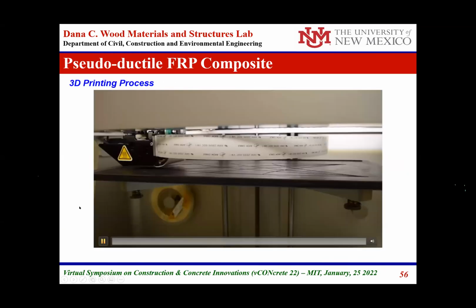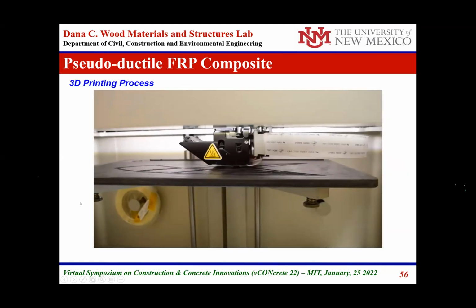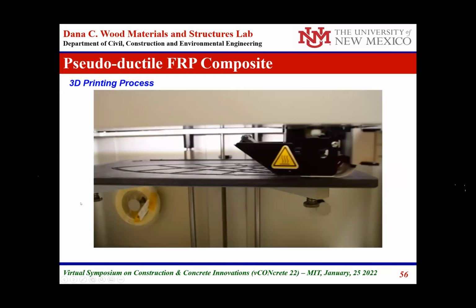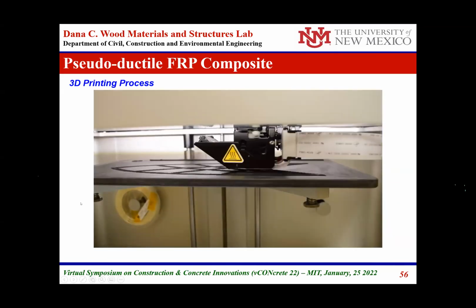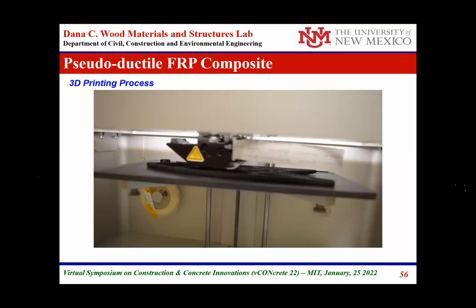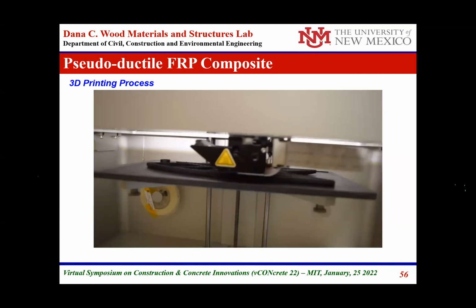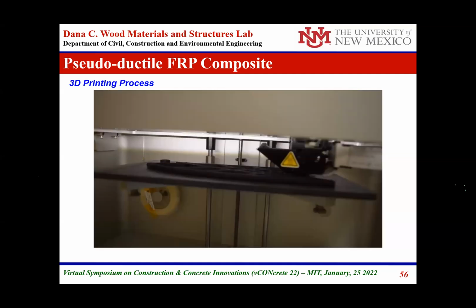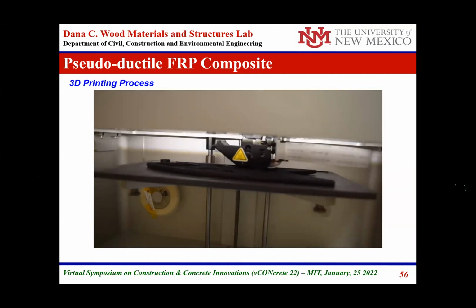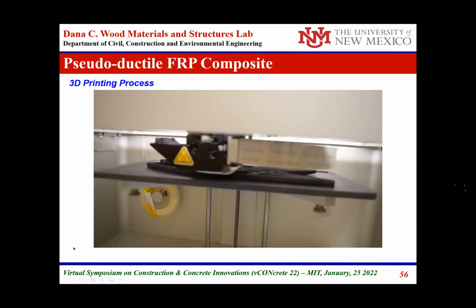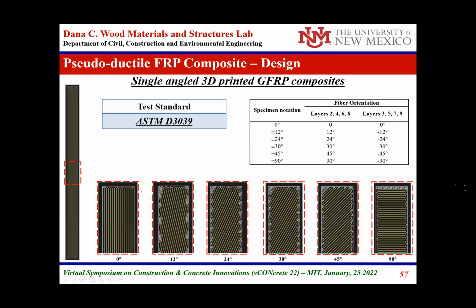So this is an example just to show the 3D printing of reinforcement, an FRP reinforcement that we decided to make to have a shape that is topologically optimized. With the interest to show that we can control the layers, we also can control the geometry of the FRP if we need. So the idea here is that when we are printing, rather than printing the FRP all in the same direction, we can change the different layers we are printing.